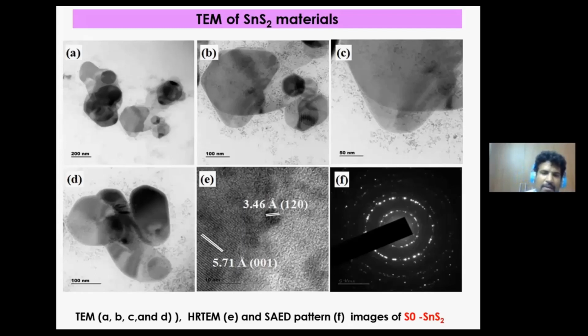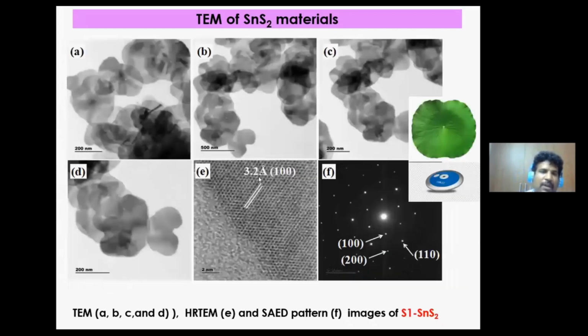So after doing this, we wanted to know the TEM image of tin disulfide synthesized using three different solvent combinations. Here, the secondary particle is completely controlled. As we have seen in the SEM, the edges of this particle are not defined. So it looks like a lotus leaf, and based on the orbicular structure that appeared in this particular area, the arrow mark area, it looks like a discus throw sporty equipment. So maybe the center portion of this material, the leaf structure, has higher thickness than the edges. The edges were not defined.